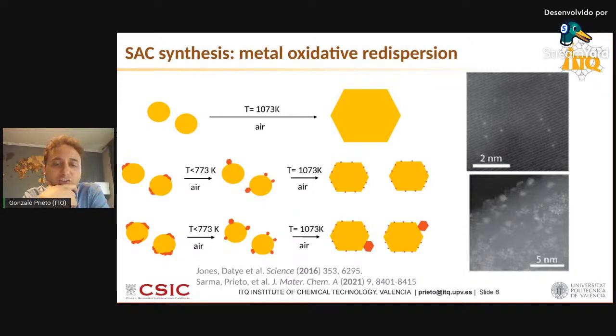mid-row in our cartoon, the synthesis goes by first depositing a metal precursor, which is depicted in darker orange, on the surface of an oxide material, which is the support, the yellow material. Then if we apply typical conventional thermal activation treatments such as calcination at relatively mild temperatures, typically below 500 degrees C is enough, then we decompose our metal precursor, and typically this leads to metal oxide crystallites, for some metals even already metallic crystallites supported on the oxide material.